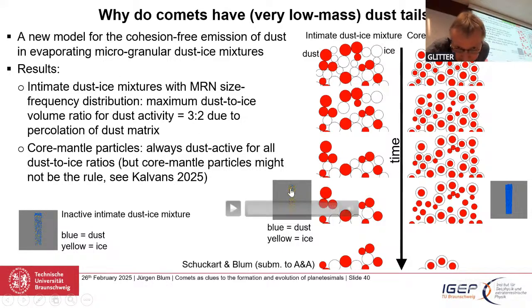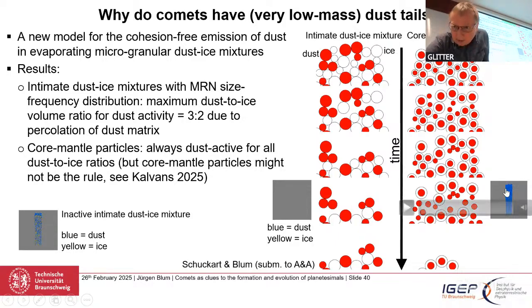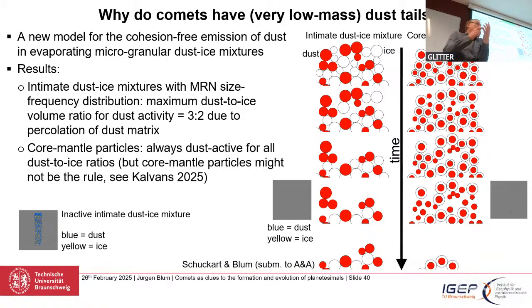So the blue color is dust, the yellow is ice. It's periodic boundary conditions. So this is just 1D depth, and the rest is periodic. And you see, this is dust active all the time. So the ice evaporates, and the dust is being emitted by, of course, a gas flow, like in a cometary surface. For a dust-ice coating, that naturally also goes. Color means the size here, because every particle is coated in ice. Also, that is active until the whole sample is gone. If that was the case, the comet would expel all its dust mass into the tail. It only expels a small fraction into the tail.